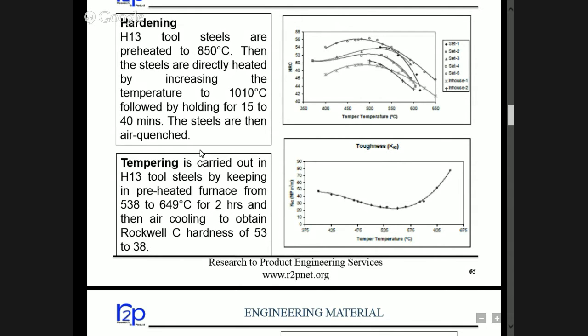So the benefit of air quenching is distortion will be very low. So we can cut the profile of the component we want to make, and by this it's a simple quenching only, so the distortion will not be severe. And then to toughen, because in case of a forging, drop forging, the impact is huge. So we need to temper it. So tempering is done at a lower temperature, maybe 5 to 600 degrees centigrade, and then air cooling to obtain Rockwell C hardness 53 to 38. Right. So we have to restrict the tempering temperature in this range, because if we take it higher, then the hardness will drop. So the more the tempering temperature, the more the ultimate hardness can drop.